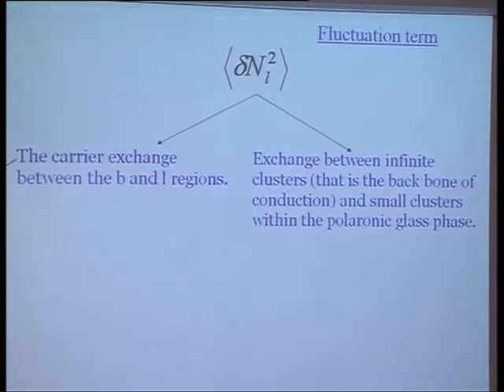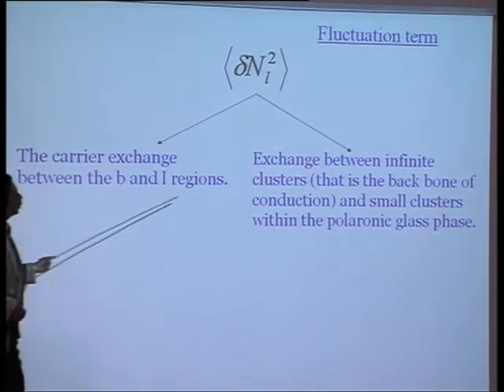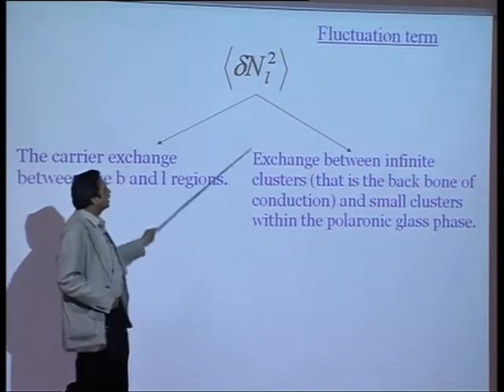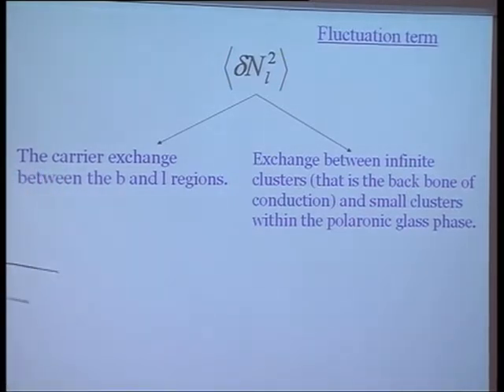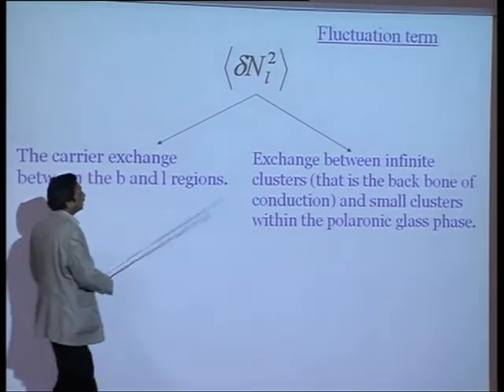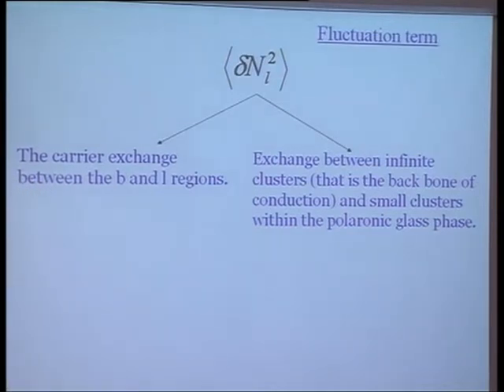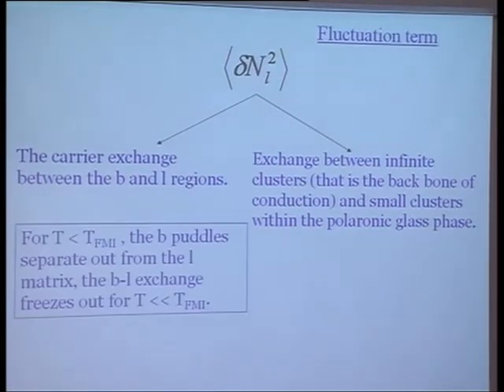Now, this term will vary because you are getting a carrier exchange to the L regions. It's a polaronic glass kind of phase they are talking about. So there are small clusters and there is an infinite cluster, and there is exchange between these two clusters. If that happens, then this is what is going to be your main source of fluctuation.